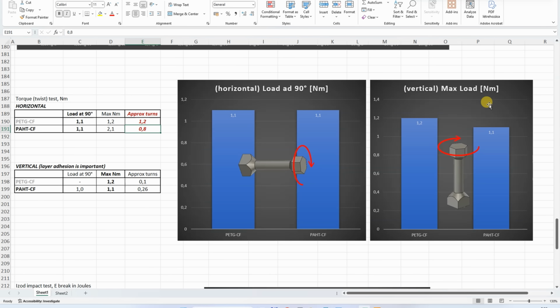Now printed vertically, 1.1 Newton meters, which is fine, but what is interesting here is that I could measure even the load at 90-degree rotation, which is quite rare. Usually it breaks more suddenly, so even against this weaker layer adhesion, this is a very promising material.